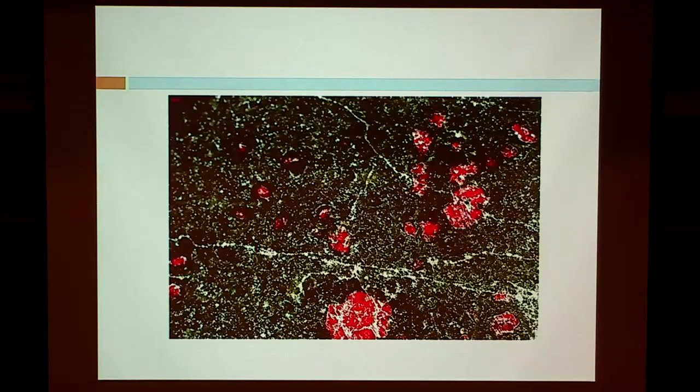And so one way of formulating our central problem is to specify a pressure, a temperature, and a chemical composition at some point in a planet, and then calculate which phases are present, what their compositions are, what their physical properties are, and then put all that together with some kind of composite theory, Voigt-Reuss-Hill or Hashin-Shtrikman, to determine the bulk physical properties of the rock.